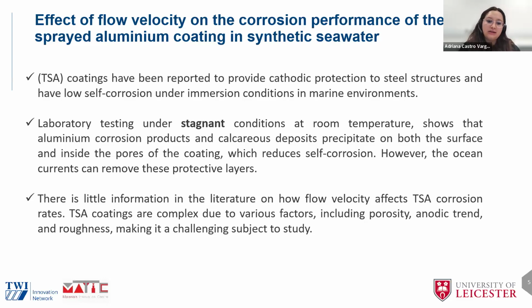These coatings are complex because of the porosity, the texture and roughness, and it's challenging to study them and give a quantitative value of the rate of degradation. For instance, there are some studies that report the corrosion rate based on mass loss for this coating. However, it might not be practical because the pores are filled with corrosion products.